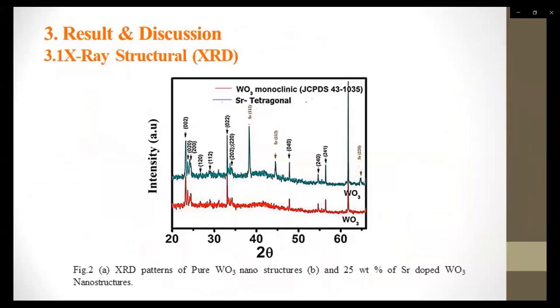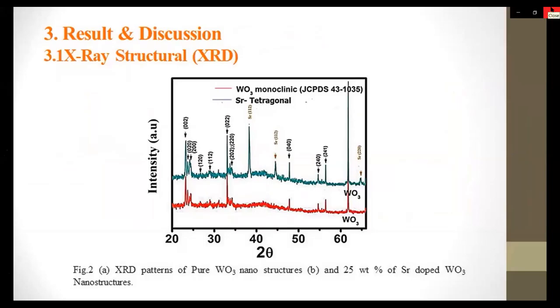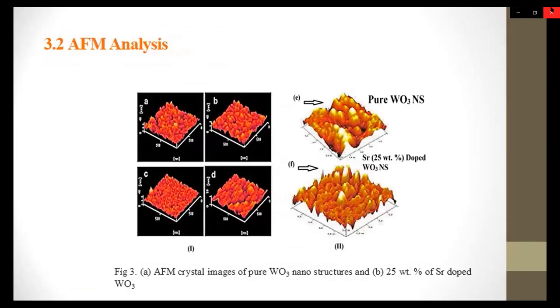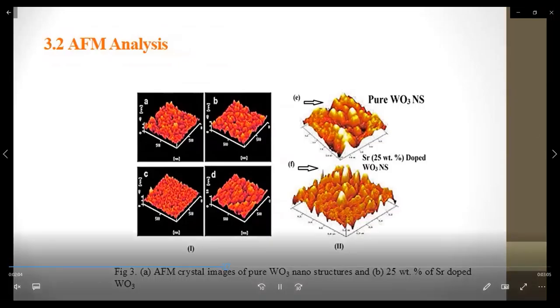This is the XRD pattern of WO3 monoclinic and Sr-doped WO3 with a tetragonal structure, with a shift in the intense peak, confirming the transformation from the monoclinic to the tetragonal structure. The 25% sample was recorded for XRD. You can see the AFM analysis done for the 25% sample. When compared to the pure sample, you can see many active sites already formed, showing the sensitivity of the surface.